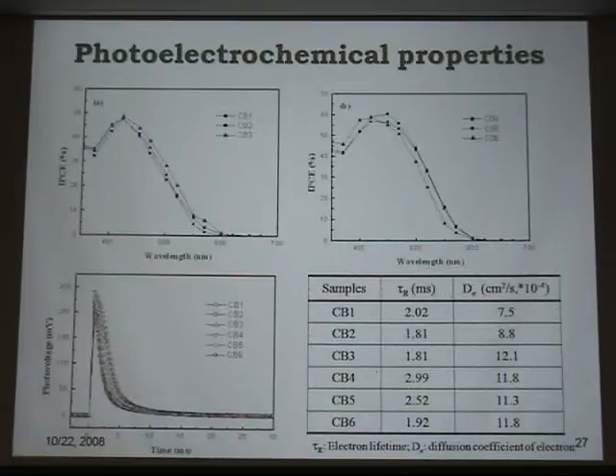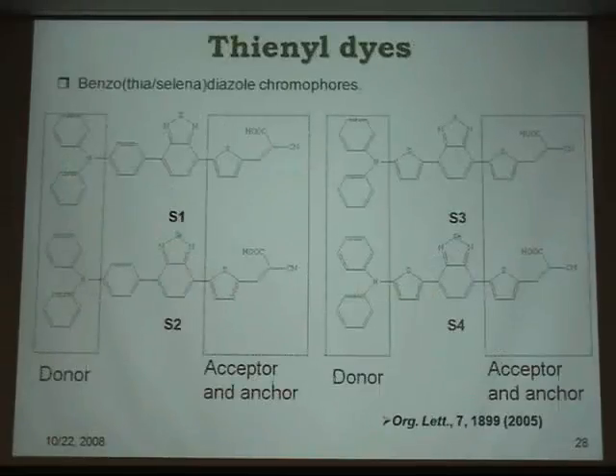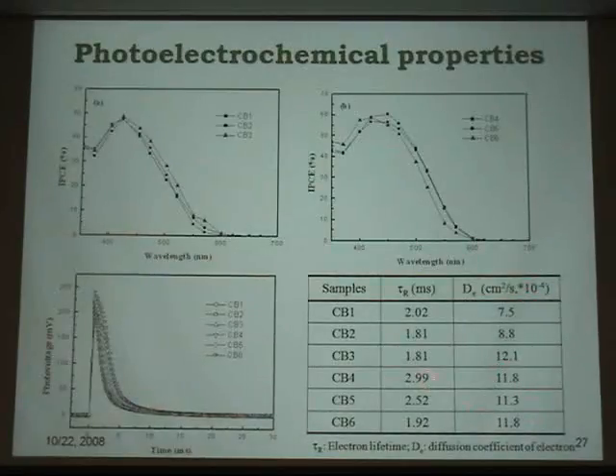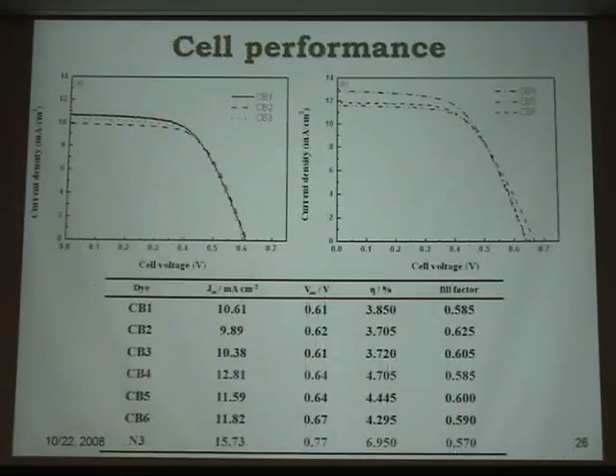So we go back to our very basic measurement, that is IPCE. It also tells us that number 4, CB number 4, performs the best in terms of high IPCE. But when we do the photophysical measurement, we find that the electron lifetime was actually the highest among all 6. The electron diffusivity did not vary much, but the electron lifetime from number 4 gives the highest efficiency. So from this regard, it is consistent with the very high performance of number 4.